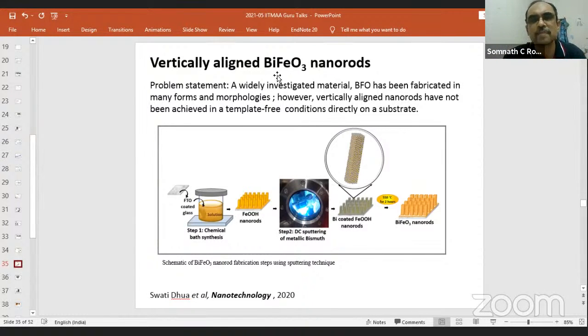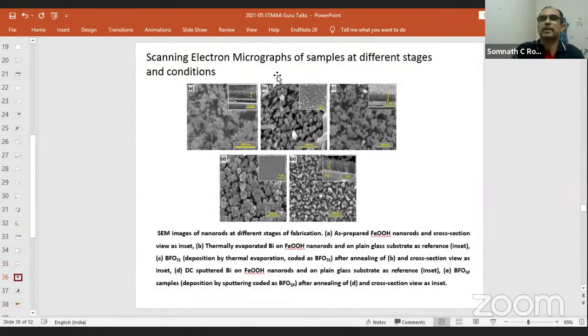So the interest in this material was there, but then around 2009, one group from Berkeley showed that they can make very good solar cells out of this material, because the ferroelectric properties actually enhance the internal electric field, which can separate the photogenerated charges much better than in silicon. So a lot of interest has grown in this material. Why we got interested? Again, our real estate business. We look for vertically aligned structures. When we looked up the development around this material, we found that a lot of work was reported.